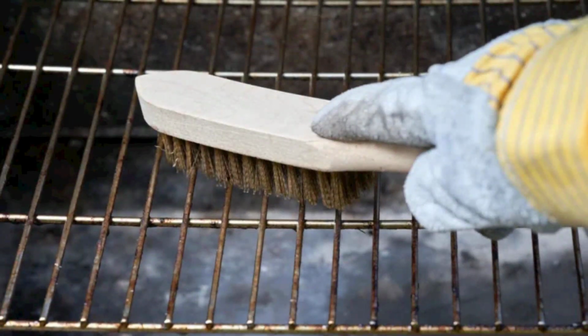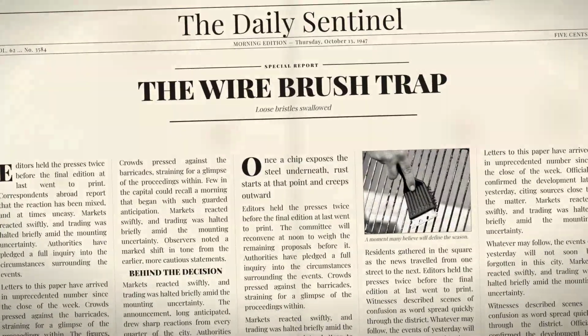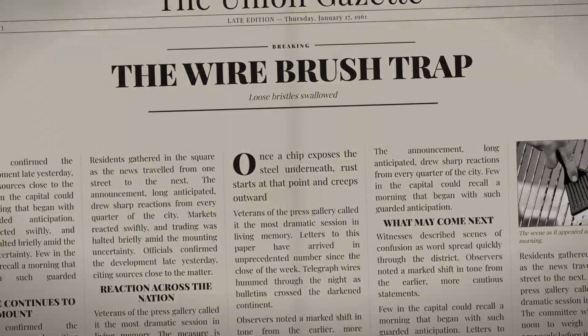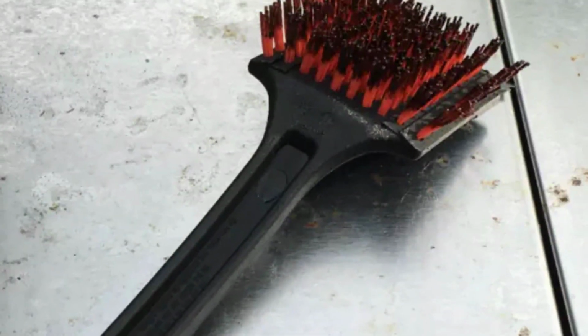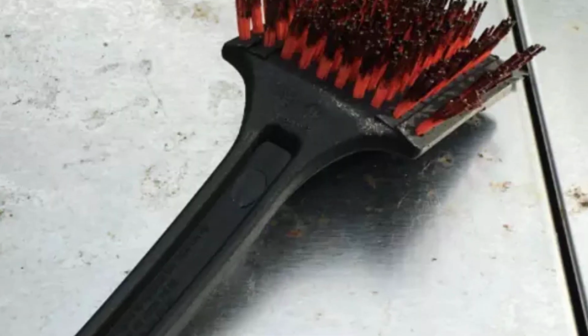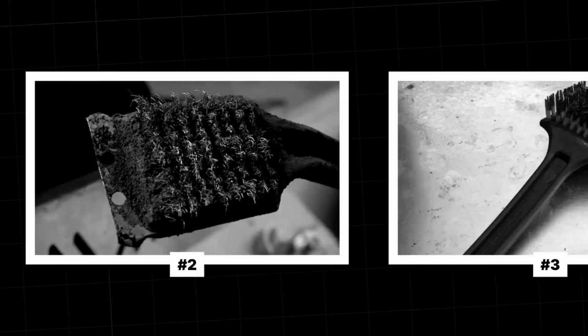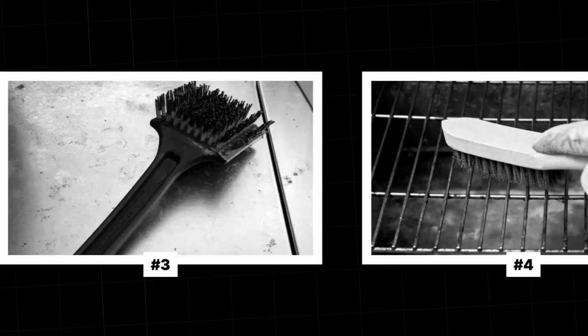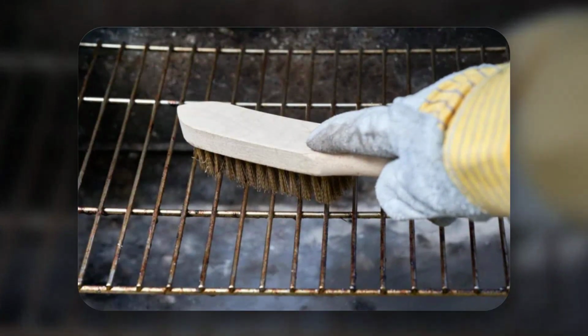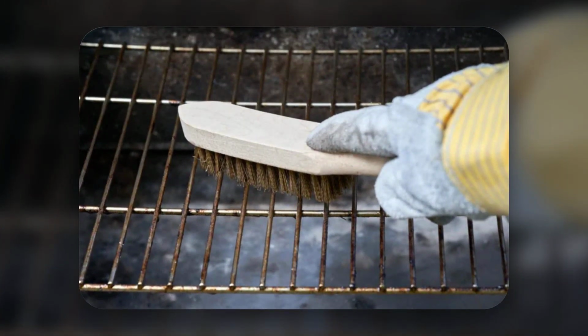On porcelain enameled grates, steel bristles chip the coating. Enamel is glass. Once a chip exposes the steel underneath, rust starts at that point and creeps outward beneath the coating, and no cleaning method reverses it. On bare cast iron, the brush strips seasoning and roughens the pores, which is the process described earlier that makes every future crust bond harder. A wire brush does not clean a grate.